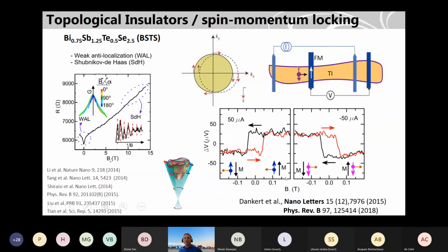When we sweep the magnetic field, we change the magnetization of this ferromagnet. For positive 50 microamp, we see this switch, and then when you come back, we again see the switch. So this is hysteresis loop like, and you can understand that by considering the magnetization of the ferromagnet and the spin direction. When you change the magnetization, the resistance changes or the voltage changes. When you change the current direction from plus 50 to minus 50, you see this reverses. So that is as expected. So your spin is now down instead of up here.